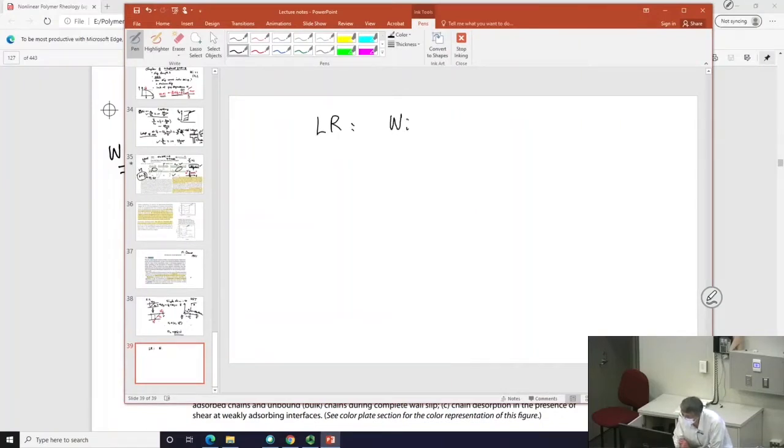Typically, if WI is smaller than one, or you may even wish to say much smaller than one, but usually smaller than one is good enough. And I hope you understand why you have linear response, because remember WI is nothing but tau divided by the time it takes to make 100% deformation. If it takes longer than tau, then your molecules are happily diffusing around. They don't care you are shearing. So the structure is preserved, therefore you have no problem.